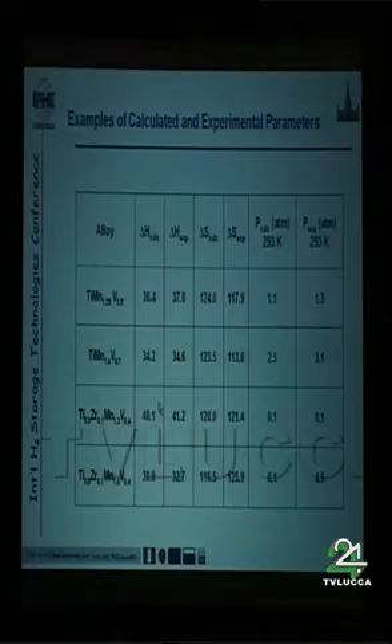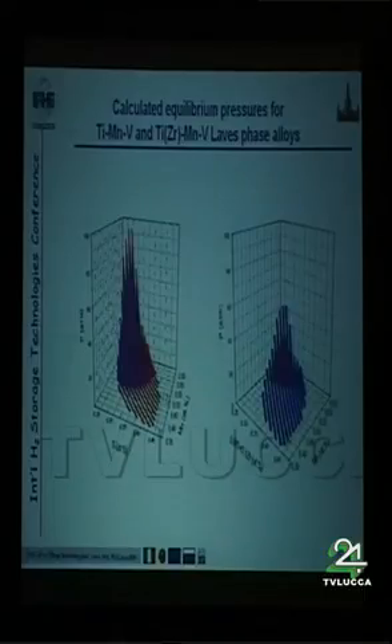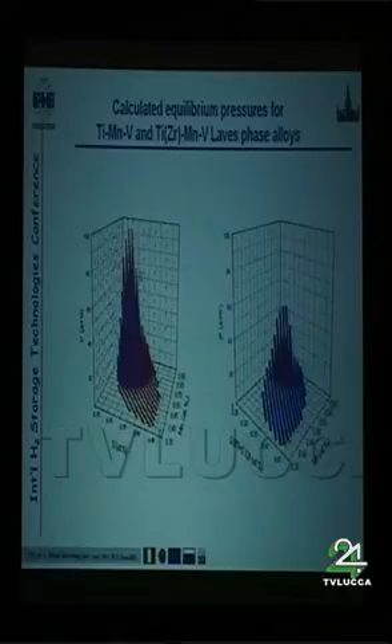Well, in fact, after that, we just calculated the whole range of possible equilibrium pressures for these ranges of Laves phase homogeneity in ternary and quaternary systems, and you can see it here.